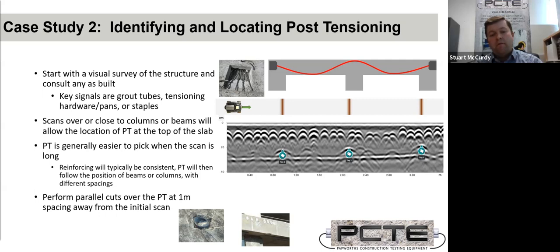Once we've identified where we think we found post-tensioning, we want to do a series of parallel cuts, because if we can find what we think is a post-tensioning strand multiple times along the path of it, and dropping in depth, which is what we expect with post-tensioning for it to sag, then we can confirm that that's the post-tensioning.